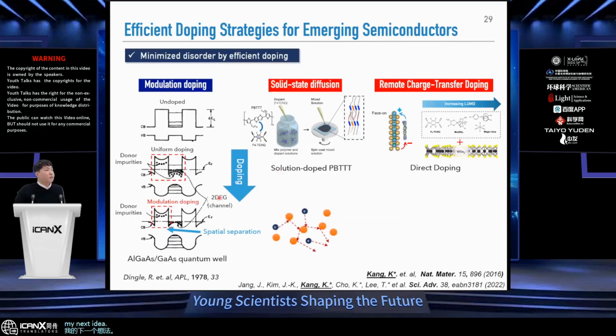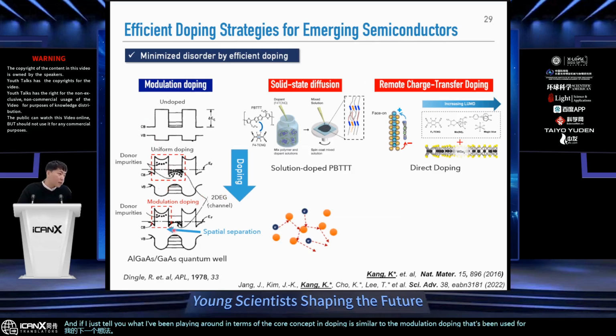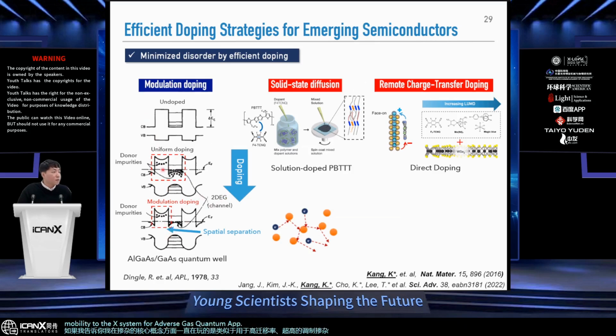My next idea. If I just tell you what I've been playing around with in terms of the core concept, it is similar to the modulation doping that's been used for ultra high mobility 2D electron gas in quantum wells, where you are spatially separating, instead of uniformly doping the channel as well as the barrier, you're only doping the inactive area of transport, and via energetic offset, you are diffusing in the charge carriers so that the channel is depleted of the ionized impurities, which reduces the scattering effect. And therefore, you are preserving the mobility of the channel, by minimizing the charged impurity scattering by physically separating the dopants in the semiconductor.